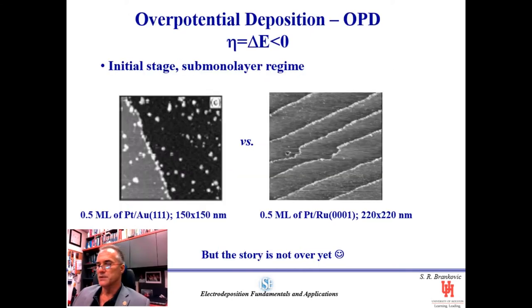Why this is important to appreciate is that sometimes, depending on how we do electrodeposition, at what overpotential we run the process, we could have interestingly nucleation of the deposit which could be preferential on the defects. Typically, in this case, we can only saturate the defect sites with nuclei, while no nucleation happens on the terraces. And that is the case when you have very small overpotentials. If you look at the same amount of material deposited using very much higher overpotentials, we can see that nucleation happens also on the terraces and on the defects.